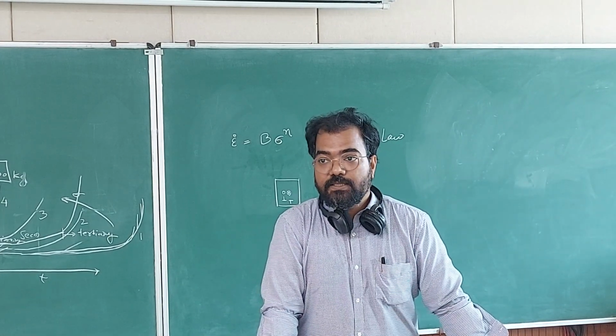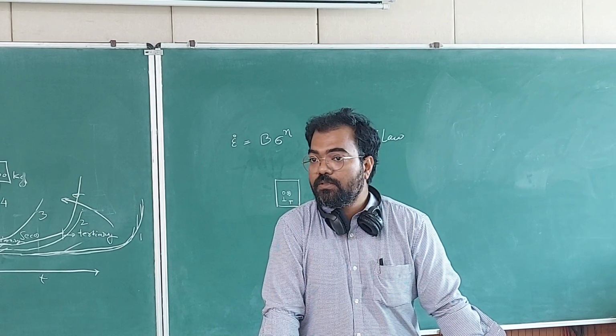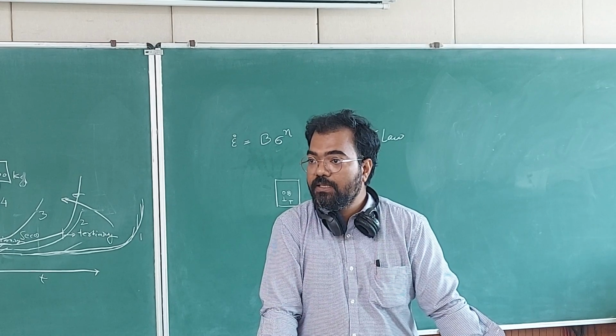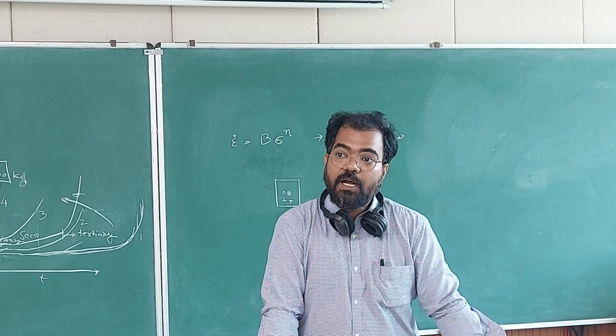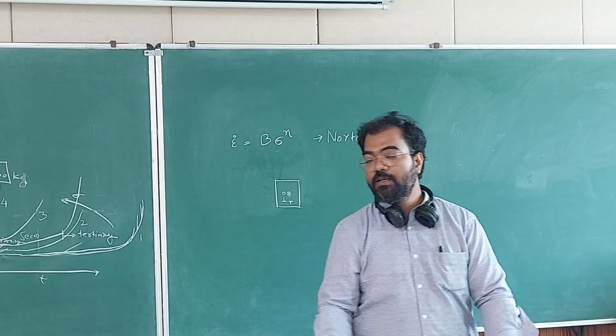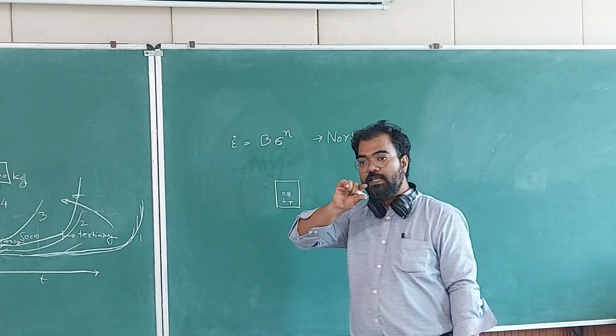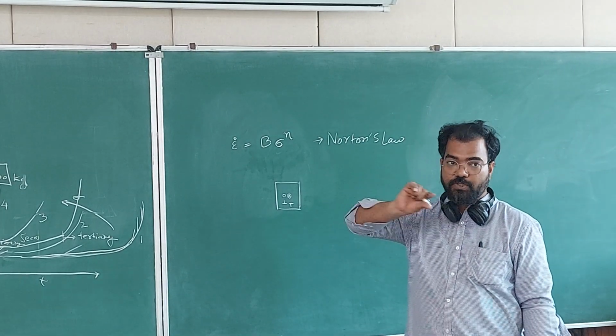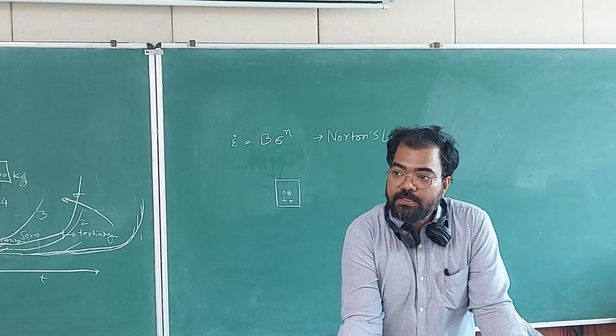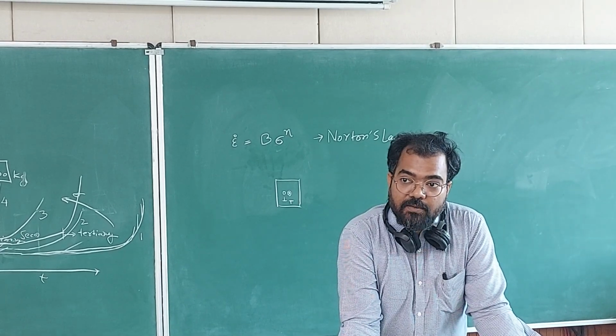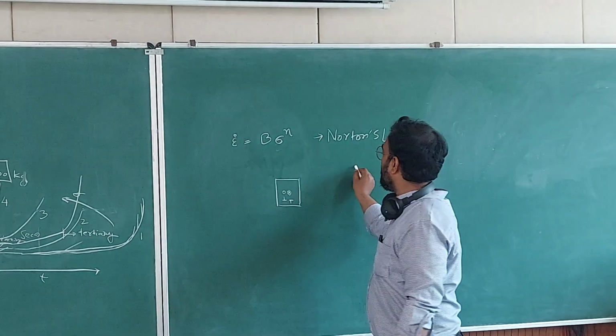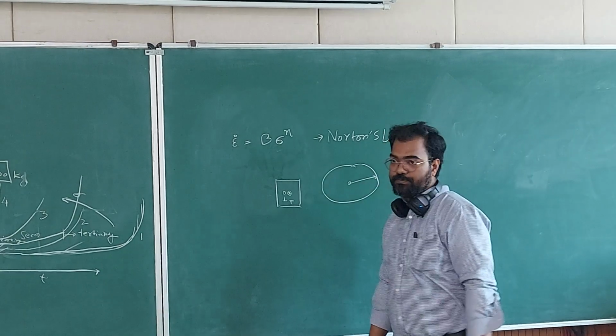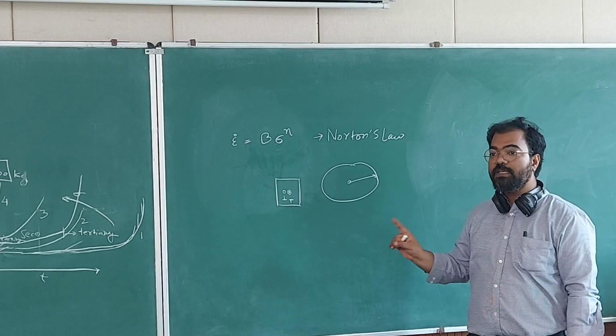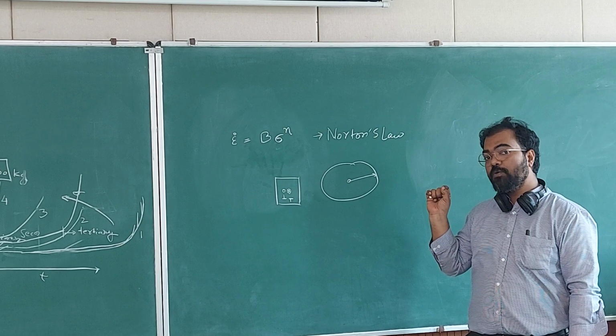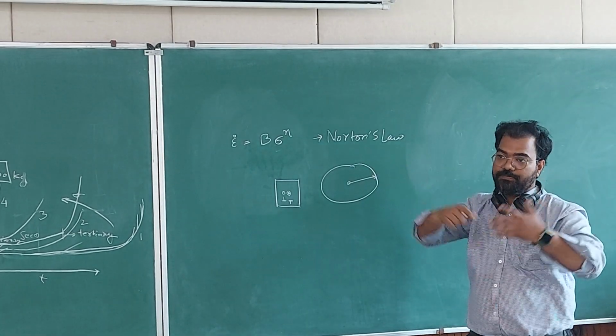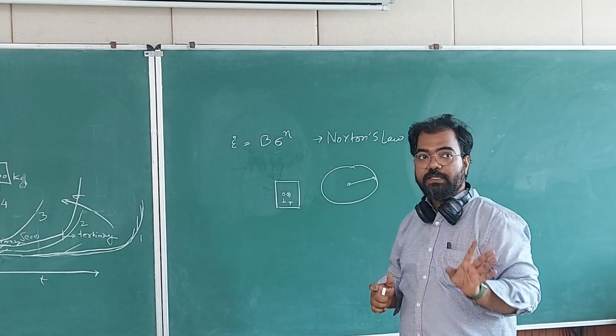Okay, so in certain cases grain boundary decides how much of diffusion based phenomena can happen, because that is defining how many vacancies can come up and how many dislocations can be absorbed and things like that. And grain boundary, apart from, so what is happening in climb, the diffusion is happening through the core of the dislocation, which is pipe diffusion. Okay, if the diffusion happens on grain boundary, then it matters what the grain size is, because the slowest process for an atom will be to go from the center to the grain boundary. Okay, so the grain size will be describing the diffusion phenomena which is based on the grain boundary. It will also be defining the diffusion which is happening through the grains. Okay, so similar to self diffusion. We will discuss this in the next class. Okay.